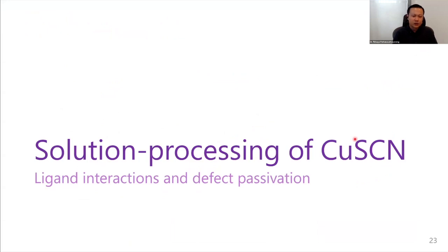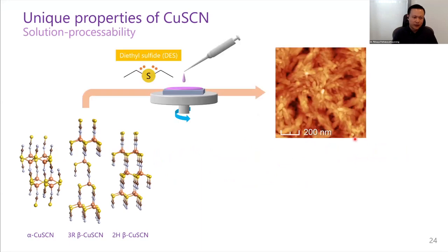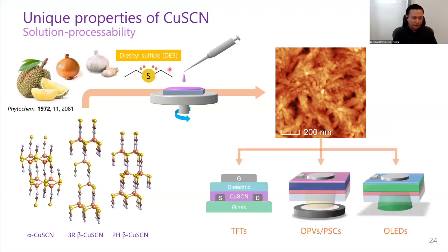But CuSCN also requires a unique way of processing. Typically we use diethyl sulfide as a solvent. So it's got sulfur and then two ethyl groups on two ends. Quite smelly because it's sulfur based, and very fittingly I'm in the district that makes durians, but it's also found as a phytochemical in durians as well as onions and garlic.